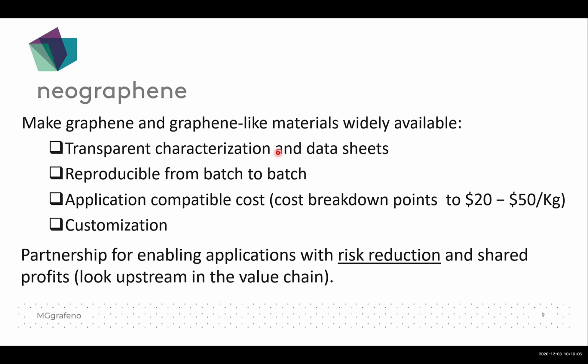So we did develop a very strong and transparent characterization matrix and data sheets. We are reproducible from batch to batch. Okay, we can demonstrate that very convincingly, and we have to have application-compatible cost. So we are looking here at a cost breakdown from $20 to $50 per kilo. We are not there, of course, still, but we have indications that we can get that in the scale up.